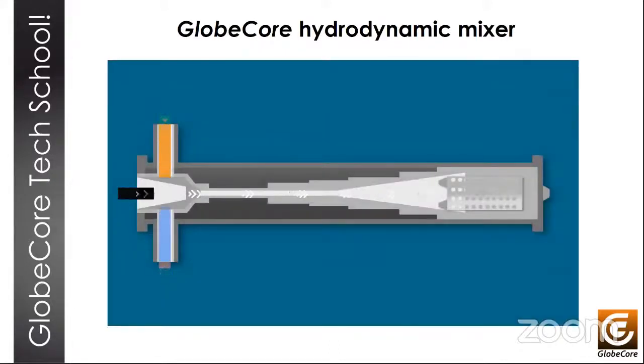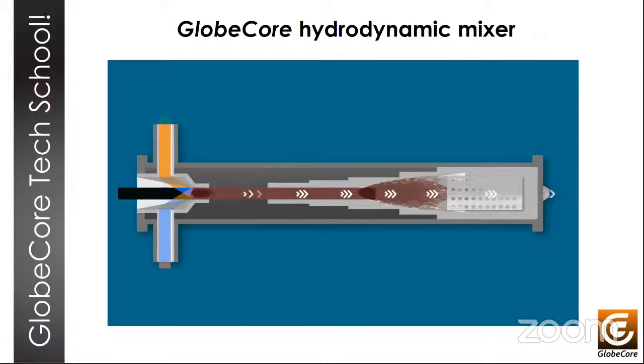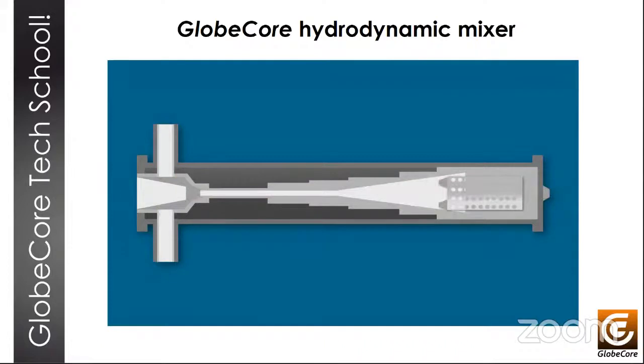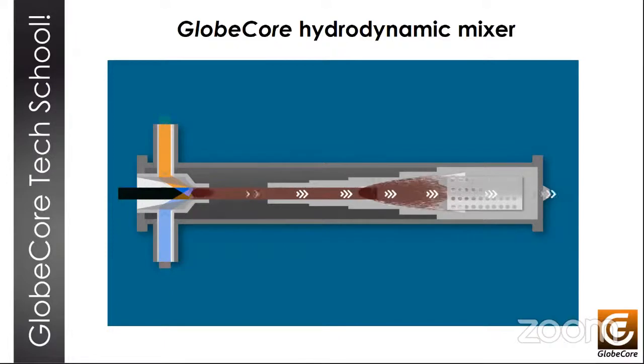So the principle of operation of Globecore bitumen emulsion plants is based on sequential mixing of components in hydrodynamic mixers at a certain pressure and temperature. Due to its unique design, the hydrodynamic mixer provides instant mixing of the components in the stream due to the sheer kinetic energy of the bitumen stream, more like a jet. It goes in at high speed, and that allows us to make the mixer rather small. This principle is used for mixing the components of the water phase, of bitumen and solvent, as well as the bitumen phase and the water phase in the end.